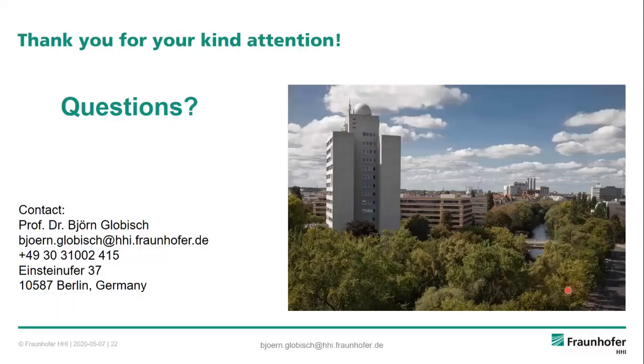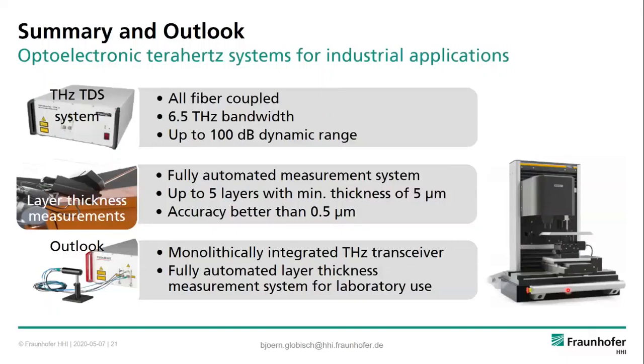Okay. I see. And we have some more questions. And the next one I see here is if it's possible to accurately measure the thickness of the superficial oxide layer of ferrous scrap materials with huge heterogeneity in shape stock in big piles. Maybe that's a very specific question. That's true. So oxide layers are typically very, very thin, right? So they are typically thinner than 5 microns. And these 5 microns are actually the resolution limit of the system. I see. Then you are right at the limit for this sort of application.